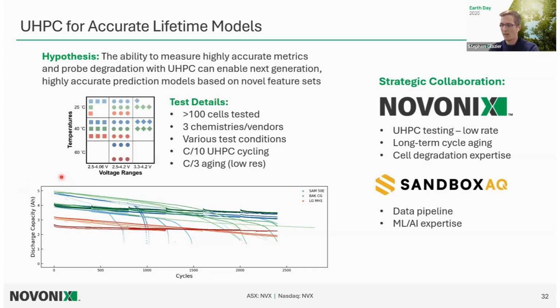And these cells were all high nickel chemistry, but they varied in anodes from having graphite in the anodes, having silicon graphite in the anode. So there's going to be a few different failure mechanisms. And to make it even more challenging to predict the lifetime of these cells, we did this at a few different temperatures, 25, 40, and 60.